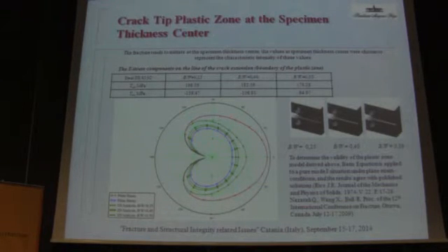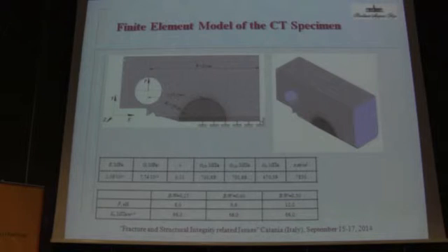To determine the validity of the plastic zone models derived above, the Irwin equation is applied to a pure mode I cracked plate under plane strain conditions. And the result agrees with the published solution in the literature. Moreover, a finite element model of the CT specimen was also conducted to validate the proposed model. And you can see the mechanical properties of the materials and the loading conditions. So again, stress intensity factor is assumed to be a constant value for this kind of specimens with different thickness.